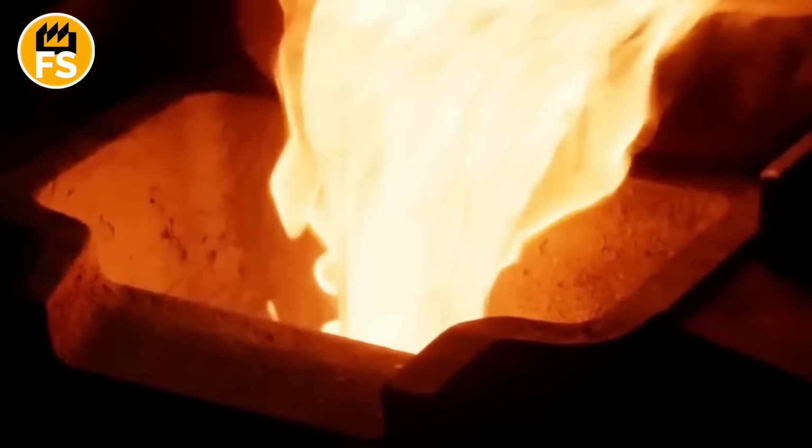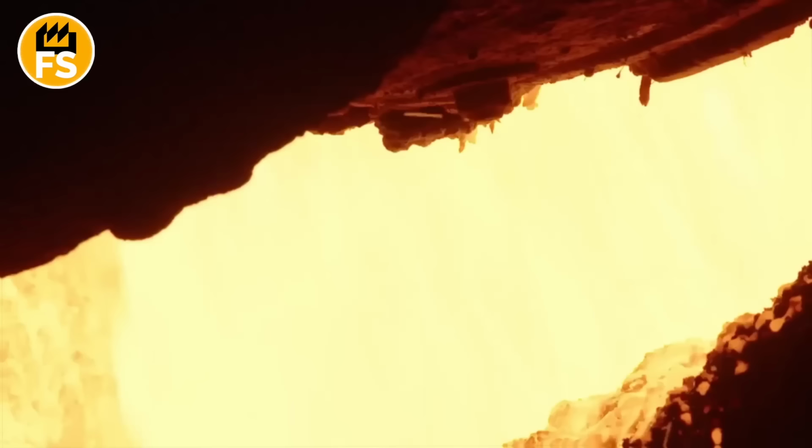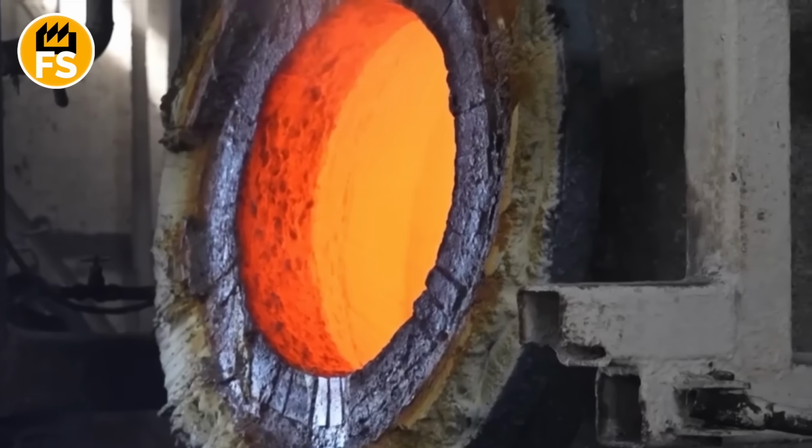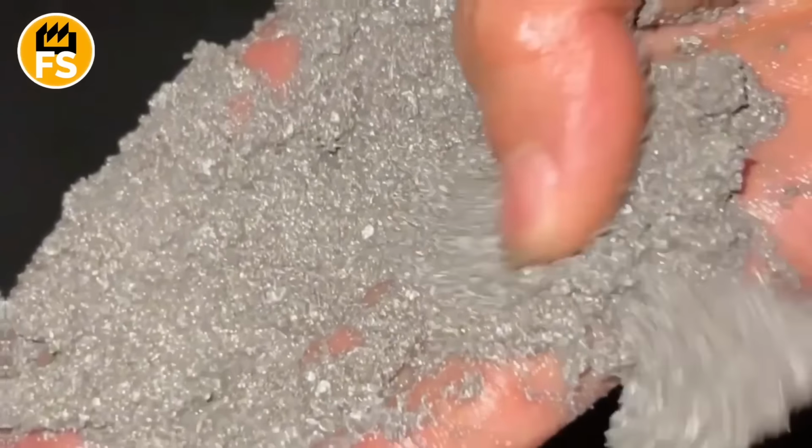During aluminothermic or silicothermic reduction, the reaction proceeds extremely rapidly and releases a significant amount of heat. Vanadium oxides surrender their oxygen to the reducing agent, while pure vanadium transitions into a molten state and immediately dissolves in the iron. The result is liquid ferrovanadium with a specified metal content, typically ranging from 40 to 80% vanadium, depending on customer requirements. After the reaction completes, the melt is held to stabilize its composition, then poured into molds. As it cools, the ferrovanadium crystallizes, forming solid ingots or granules with a characteristic dark gray surface. The material is then crushed to a convenient size, packaged, and shipped to steel mills.